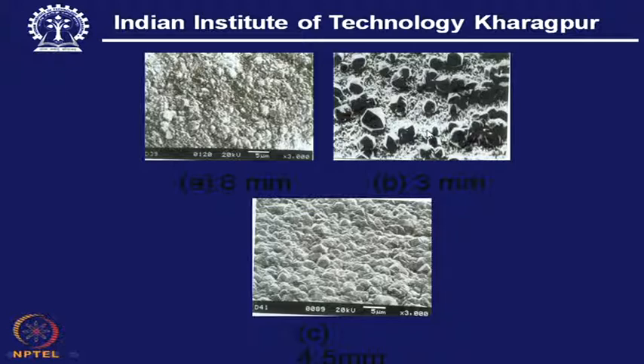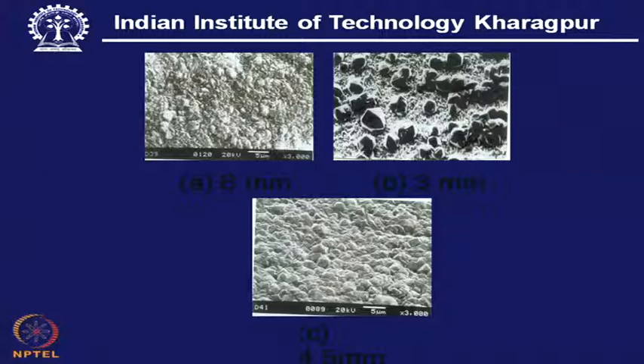Now, the whole idea here to show this picture is only to impress upon the fact that with this SEM picture, we can get a lot of information about the quality of the coating, and also with our experience, we should be able to make certain reasonable remarks or observations, not without reason, about the process itself in the upstream site, and what preventive and corrective measures have to be taken on that side. That can be well understood from this SEM picture. So, this way a lot of possibilities SEM can open up,